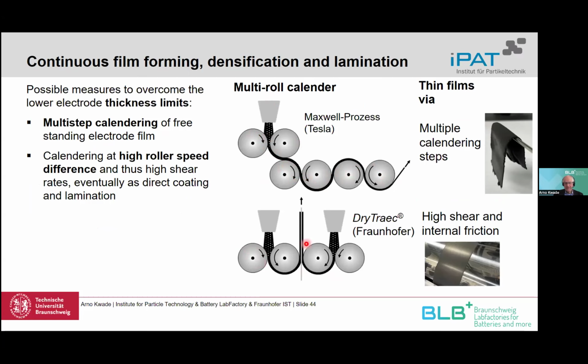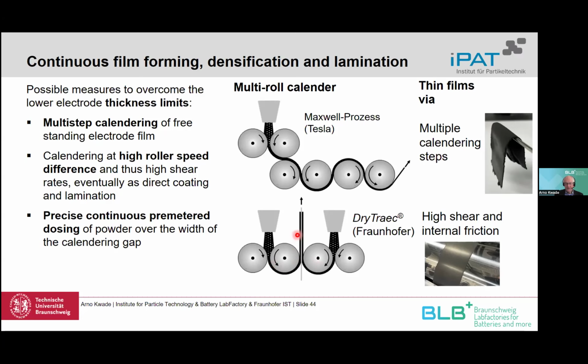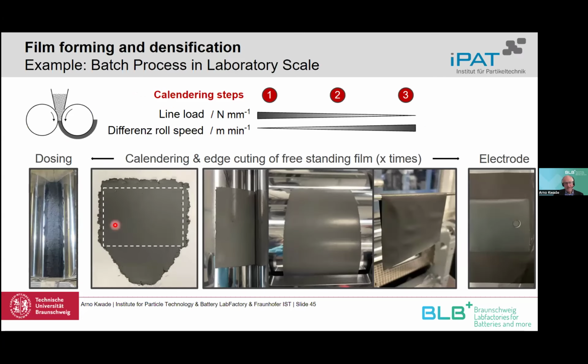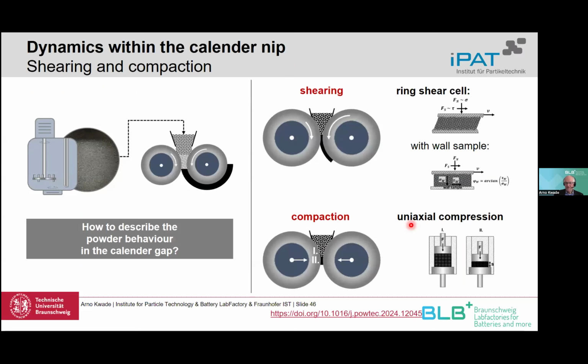And there's another dry process where we have a high differential speed of the rollers, and by that we come down to very thin layers already, and then we can directly connect it, or laminate it, to the collector. And to show how that looks, you have the powder here, you get a sheet, and by several, or in this case 3, densification steps, we get a nice film, which is really mechanically stable and can then be transferred further. The question is how we can describe that.